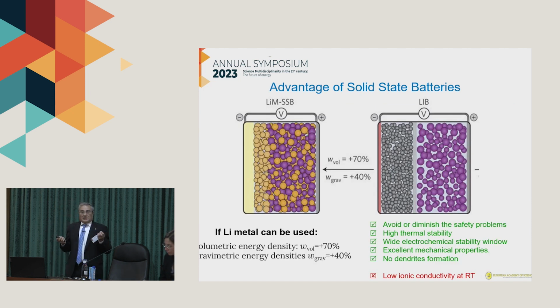Why all-solid-state batteries? The main advantages: they diminish the safety problems, high thermal stability, wide electrochemical stability window, stellar mechanical properties, and no dendrite formation if we use metallic lithium. The main drawback is the low ionic conductivity at room temperature. If we can use metallic lithium as anode, we can improve the volumetric energy density about 70% and the gravimetric energy density 40% with respect to the conventional organic electrolyte.